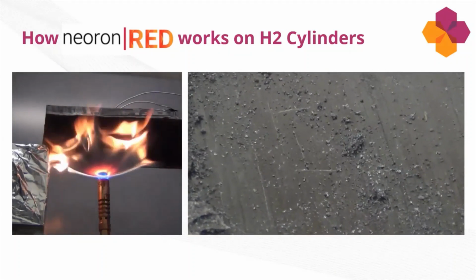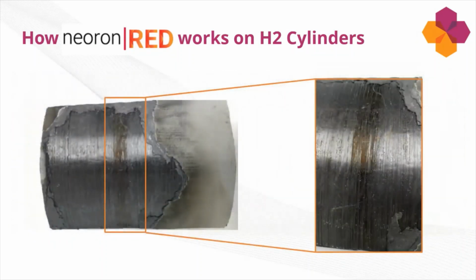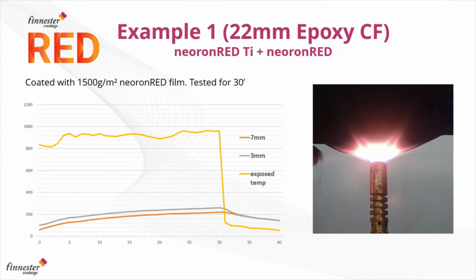And maybe the next slide will show a more precise picture. This is the afterburn. You can really see there's not too much damage on the original substrate after half an hour. If you put that in a curve, the maximum temperature was about 250 at a 3 millimeter depth from the exposed side. Between the coating and the composite, 3 millimeters to the composite, and from the coating, 7 millimeters to the composite, there's a 40 degree difference in temperatures, but it's more or less stable after 10 minutes. It stabilizes itself. Outside temperature was around 900, more or less.